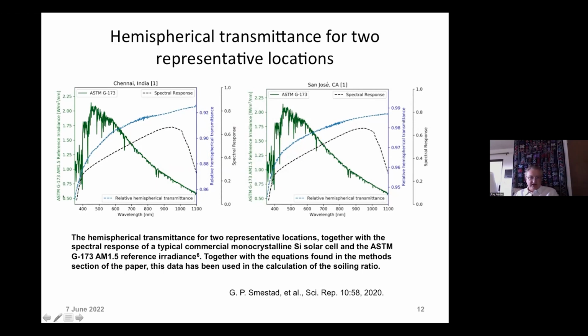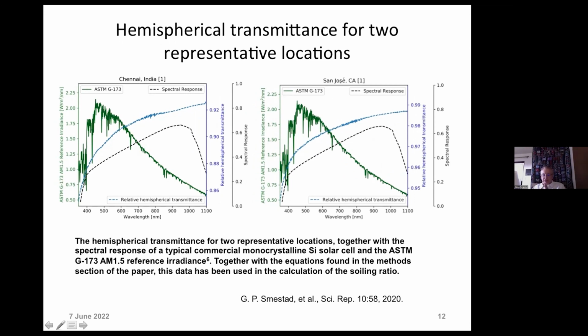So it starts out with a low transmission. Here's the relative hemispherical transmittance in the blue and UV. The transmittance due to soiling, the tau, is low. And then as we get to longer wavelengths, it becomes closer and closer to some leveling off, higher value. Not quite one, not quite unity, but at some value. So these are the three components that go into that. And you see that I've shown this for a transmittance that we measured, this blue curve, in Chennai, India, or that we measured here where I live in San Jose. So it depends upon the location and the time.